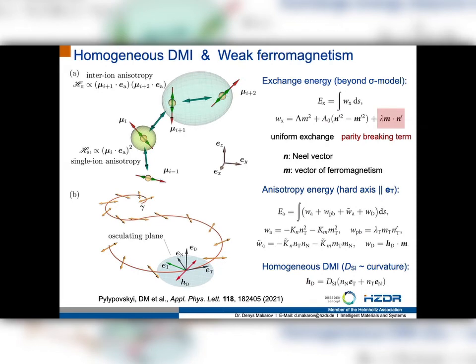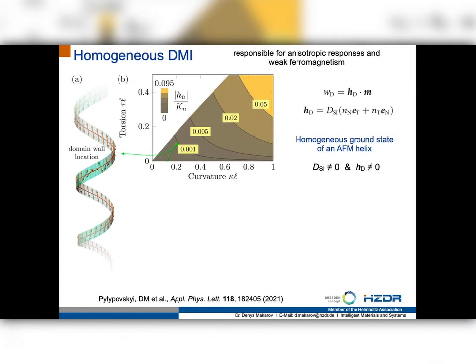As you can see from the symmetry, this term is proportional to curvature, so basically it can be observed even in flat curved curves, and at the same time you need a special symmetry of the Néel vector, where you need at least a normal and/or tangential component of the Néel vector to be non-zero to be able to observe this effect. This can be easily realized in the homogeneous ground state of an antiferromagnetic helix, where you obviously have curvature, so the coefficient of homogeneous Dzyaloshinskii is not zero, and also you have proper ingredients in the Néel vector, which allows you to get this homogeneous Dzyaloshinskii-Moriya interaction, which is responsible for anisotropic responses and eventually can cause weak ferromagnetism in a system.